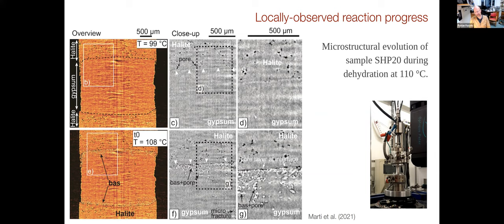Now you can see the quality of this data is slightly less good, but it has to do with the experimental setup and the beam line and so forth. But you can still very nicely see there's these halite needles growing and there's porosity between. And interestingly now, there's also porosity at the interface here with the halite, which wasn't there before. It's the same scale here.